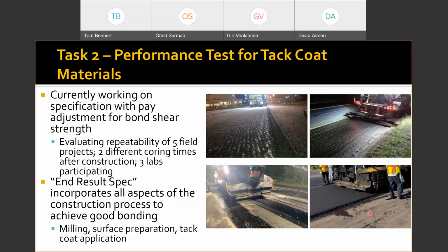This tack coat material is mixed with water in a chemical package so the oil and water do not separate. What that allows you to do is get it down more evenly at lower temperatures, so you don't have to excessively heat it, but you're going to get full distribution. But you have to allow that material to cure and what we call break, meaning the water evaporates. In this case, they started paving way too early. They actually paved over a tack coat that was still water and had not broken yet. So all of these things will impact how well we get bonding.